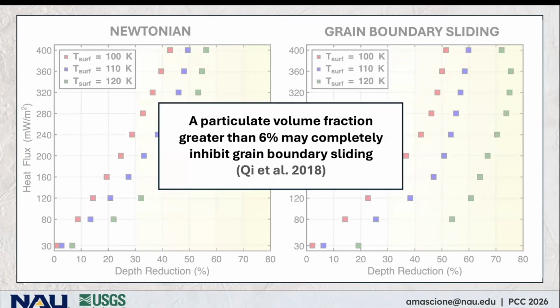A recent study found that a particulate volume fraction as small as 6% may completely inhibit grain boundary sliding. Now, Europa's ice shell likely contains some small fraction of non-ice components, such as salts and radiolytic products. And if this fraction is large enough, it could inhibit the grain boundary sliding process. And for this reason, we're also going to run the same suite of simulations under a dislocation creep dominated rheology, because dislocation creep is an intragranular process that should not be as affected by the presence of intergranular particles.